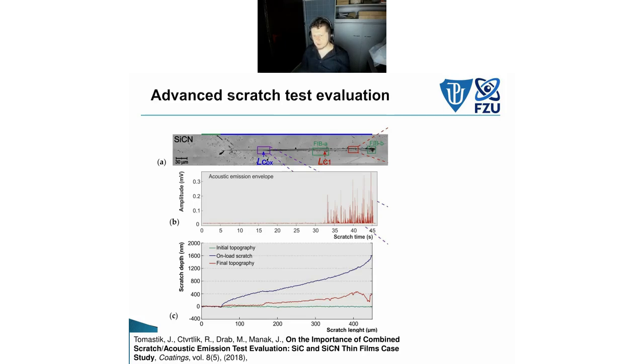Maybe an even stronger use of this acoustic emission detection system can be shown here. This is a silicon carbon nitride. As I said, silicon carbon nitride seemed to have lower hardness than silicon carbide. Okay, I didn't describe that during mechanical properties. What was apparent from the graphs is that increased nitrogen content means lower hardness, but it cannot be problematic during tribological behavior because lower hardness can mean higher ductility. So, okay, silicon carbon nitride.